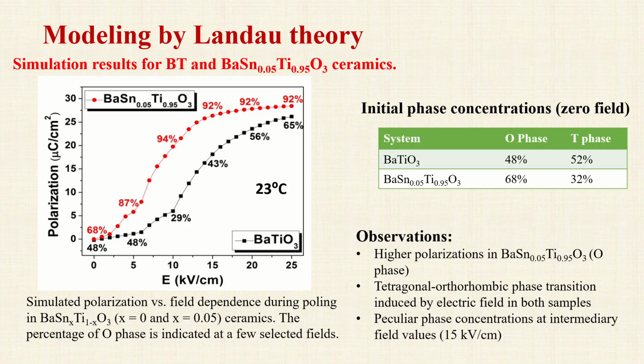Although both tetragonal to orthorhombic and orthorhombic to tetragonal phase transitions of the grains are possible depending on the grain rotations, as discussed before, we can observe that overall the tetragonal to orthorhombic field-induced phase transition is favored. This can be explained by the fact that the orthorhombic phase has 12 possible orientations and not only 6 like the tetragonal phase. Very interesting is the fact that the amount of the phases does not change monotonously, but presents peculiar concentrations at intermediate field values.